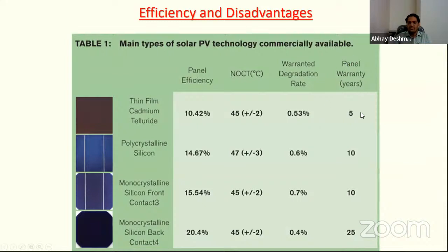And if you talk about the polycrystalline silicon, your warranty is 10 years, and panel efficiency is around 15%. And then you talk about the monocrystalline silicon front contacts, you have a 15.54% efficiency with a 10 years panel warranty. And monocrystalline silicon with back contacts, you have a 20.4% efficiency with a 25 years panel warranty.